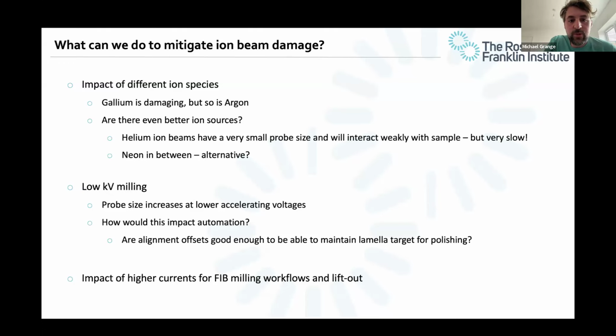Well, helium ion beams have a very small probe size. They interact weakly. The counteraction to that is, if they interact weakly, they're not going to mill very quickly. So there might be some trade-offs one day. Neon ion beams are used quite commonly, I think, in material science as well, and they have a potential for a lower degree of damage. But these all need to be tested, obviously.